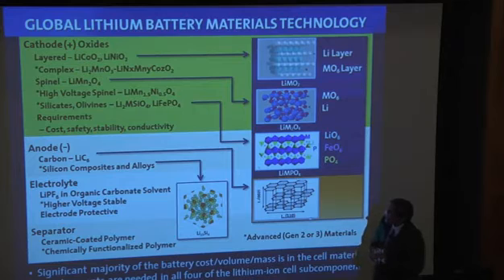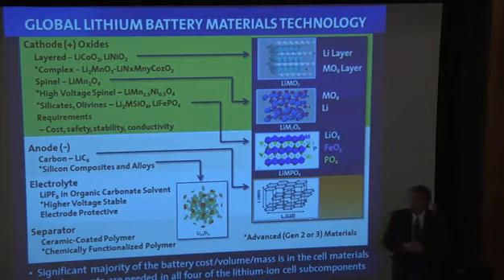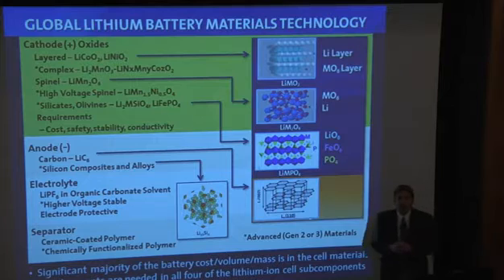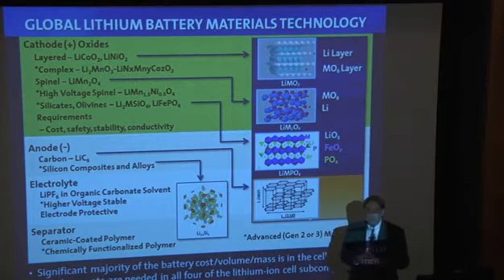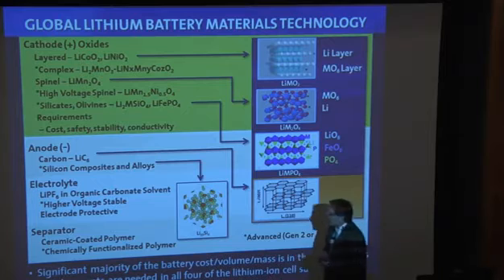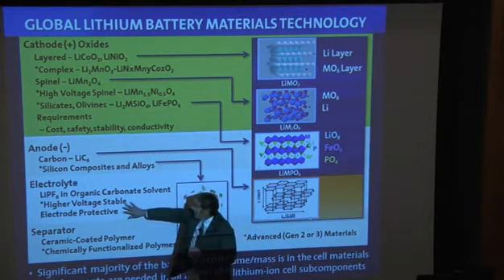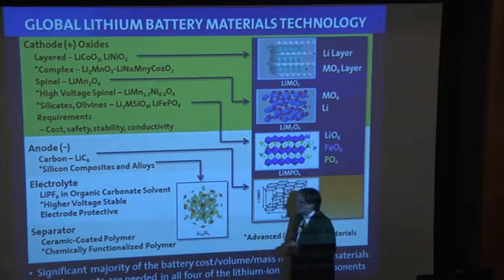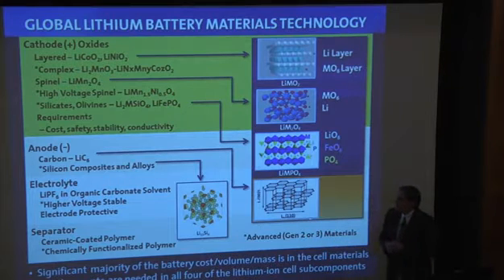High voltage spinels, it's a different variant where you now have a manganese nickel spinel system. You operate at about 4.8 volts there. The challenge is to get a high voltage stable electrolyte. You'll see down here, high voltage stable electrolyte system is something that's still out there that hasn't been developed. As you come down into the negative electrode, the anode on discharge, carbon is the standard today.